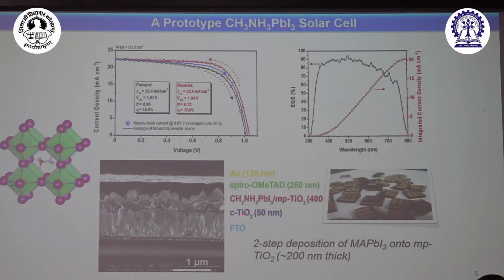And on that one, you are putting a compact TiO2 just to break the barrier of FTO. Then you are putting a mesoscopic TiO2, and on that one, you are putting methyl ammonium lead iodide. And that's what the thickness is. This is your whole conducting layer. In this case, it's spiro-OMeTAD, and on the top, there is a gold contact. So if you see it, the entire thickness of all these layers is almost the same as your FTO layer, less than a micron thick. That is the beauty of it, because you can do this thin film deposition and get it.